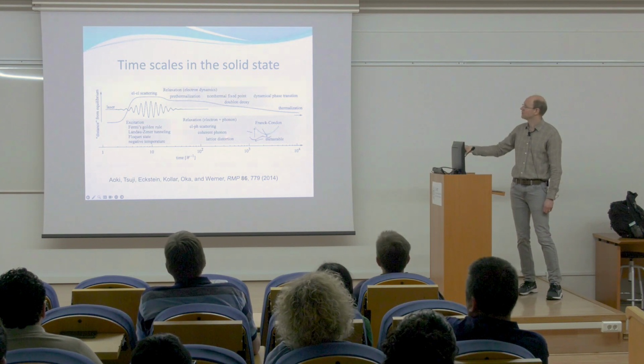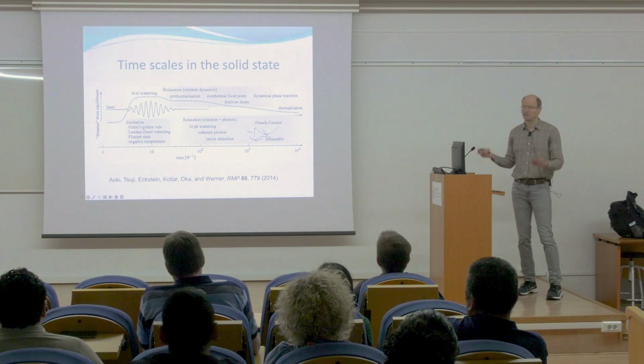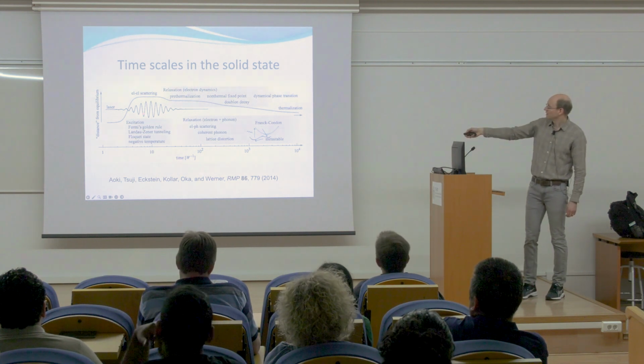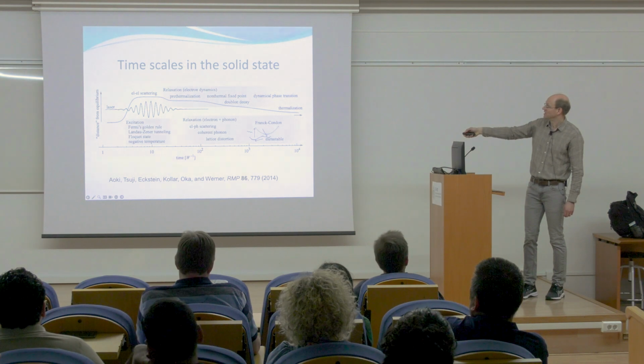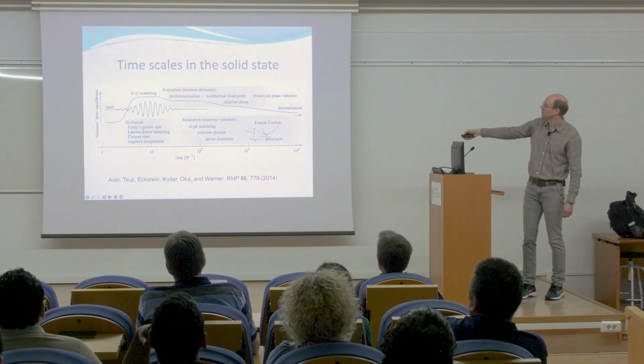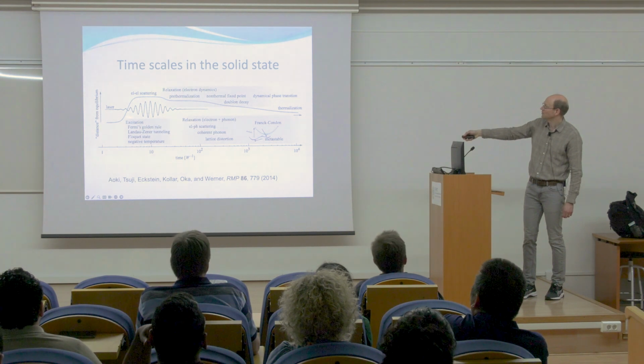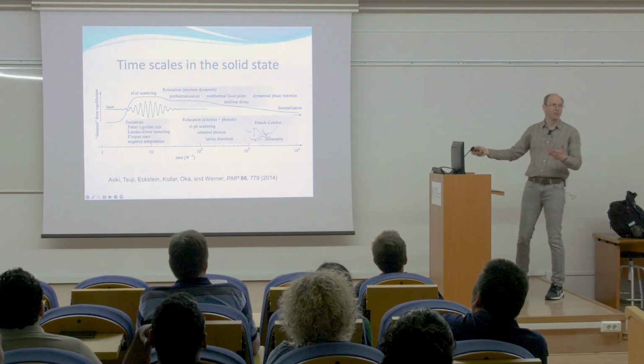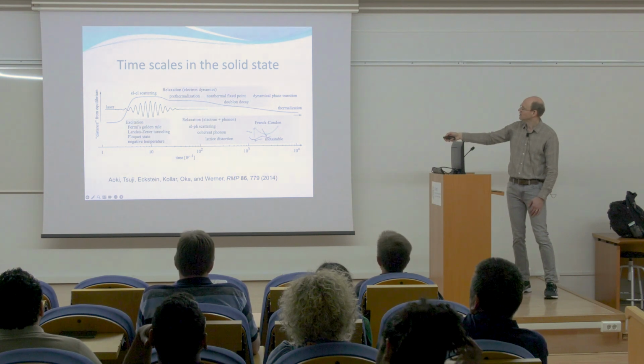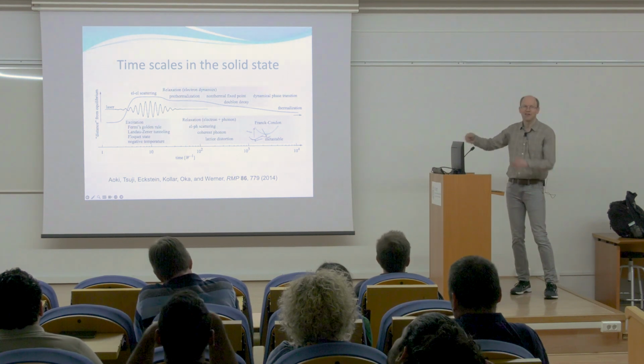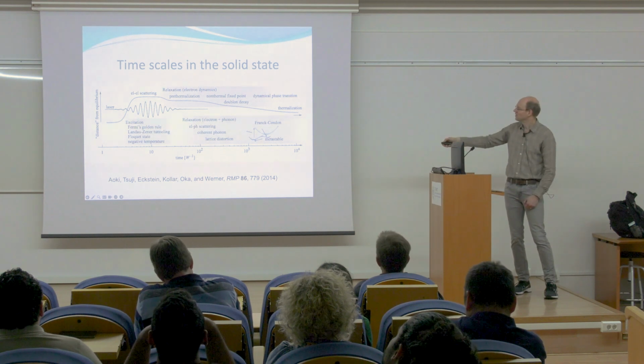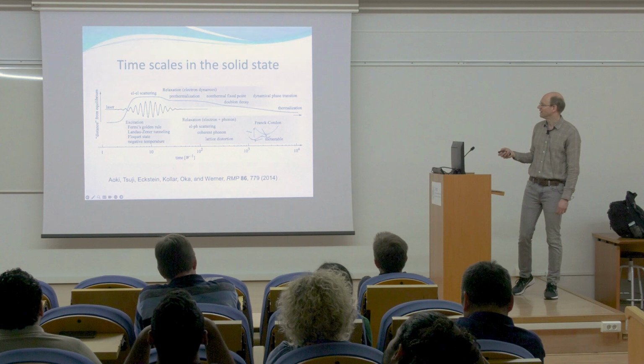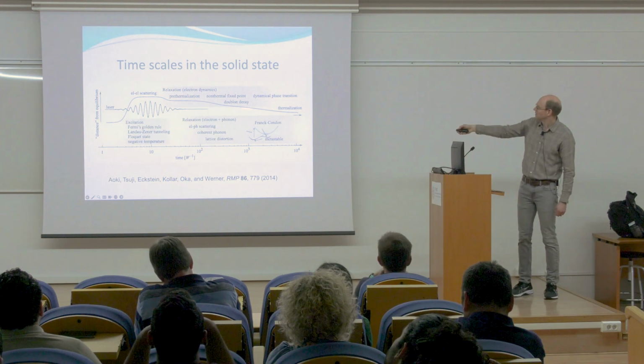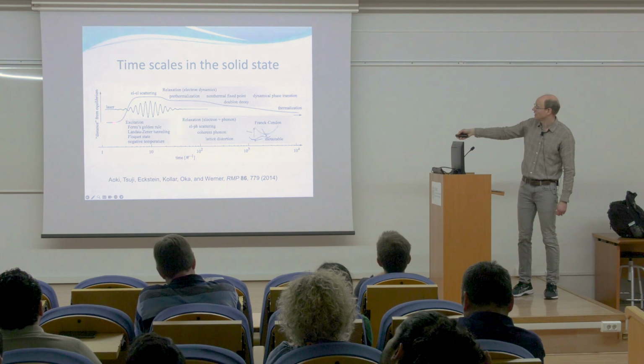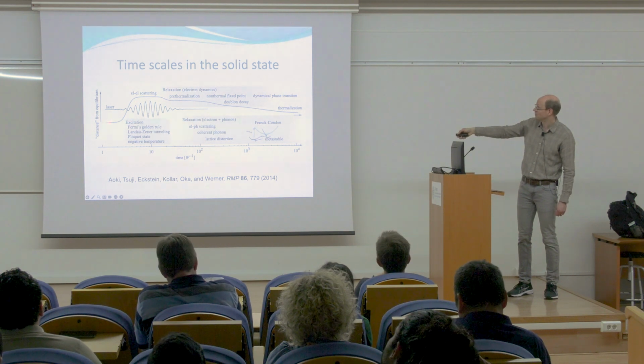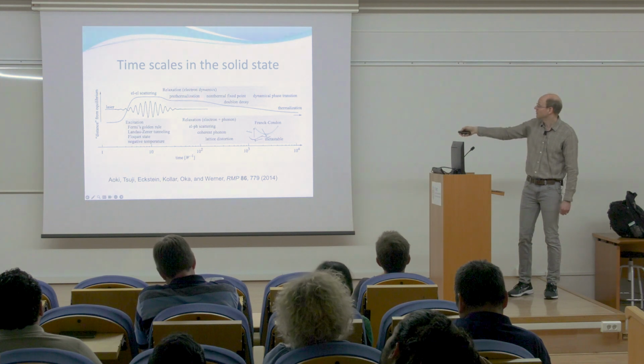But anyway, this will give you a sense of the degrees of freedom and the various time scales that are typically encountered in a material. So here's a schematic of a laser. There's typically a Gaussian envelope, with oscillations within the envelope. This one would be more like the long pulse limit, with many, say of order 15, oscillations within this Gaussian envelope. That's enough so that near the center it looks kind of Floquet-like. The blue curve is showing the trajectory of the system. You shine light on the system, you excite it, so you're farther away from equilibrium, and then over time you relax back.